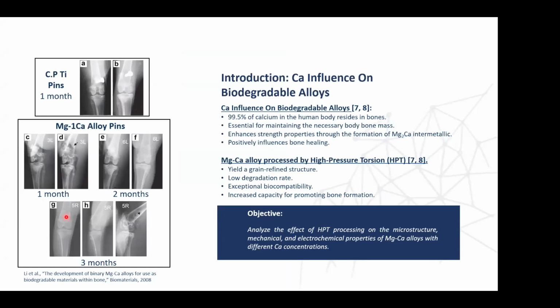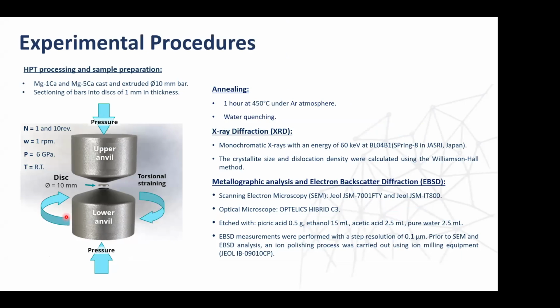Some people have, of course, used magnesium calcium as a standard alloy for controlling or testing as a potential material for biodegradability. So we did HPT on magnesium calcium alloys. 1% calcium and 5% calcium were what we tried firstly and most successfully. And we did a very similar processing and characterization as we did for the titanium alloys.